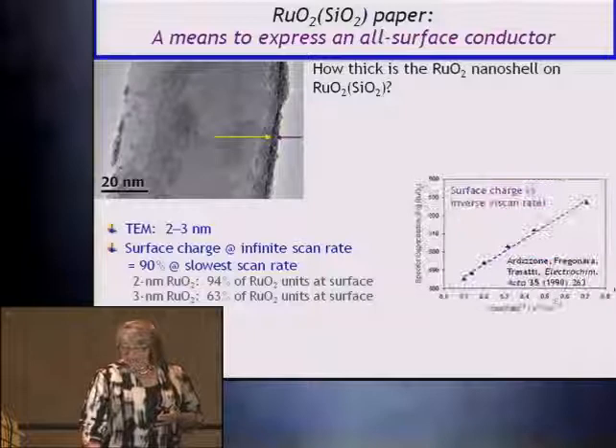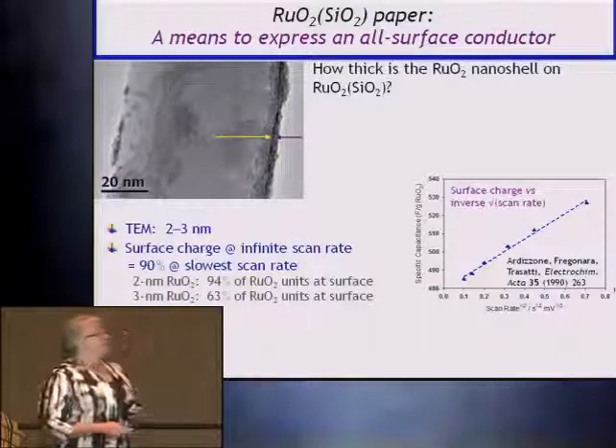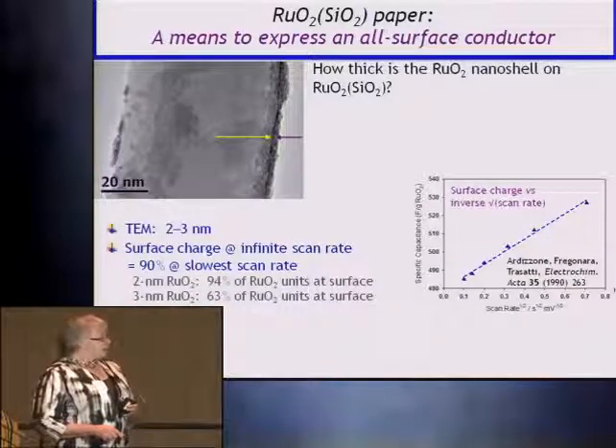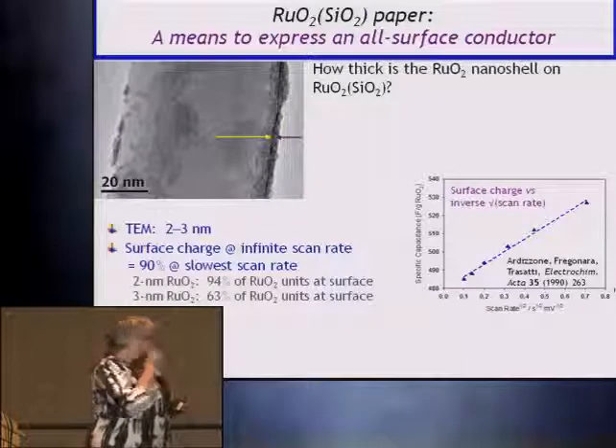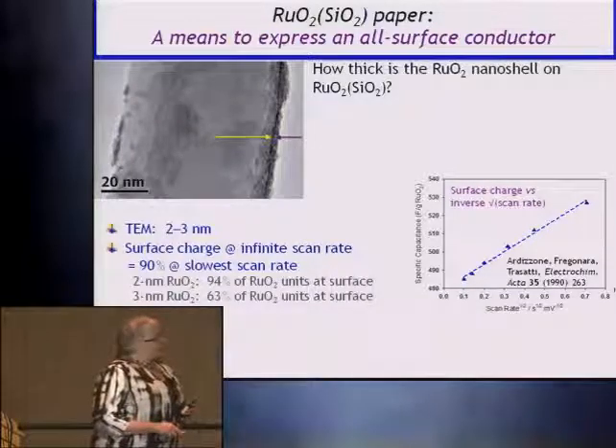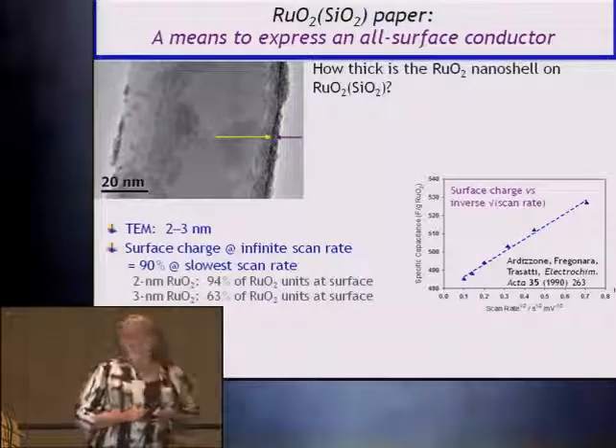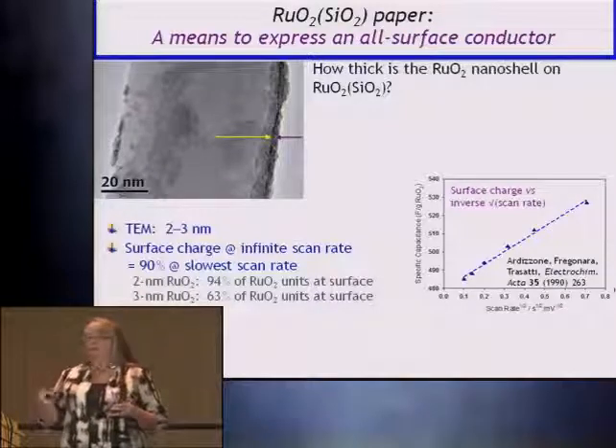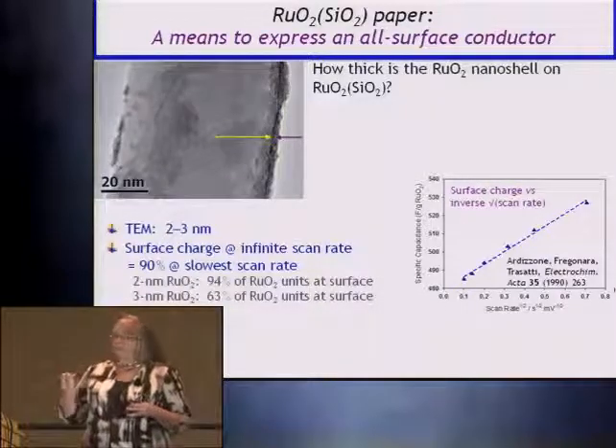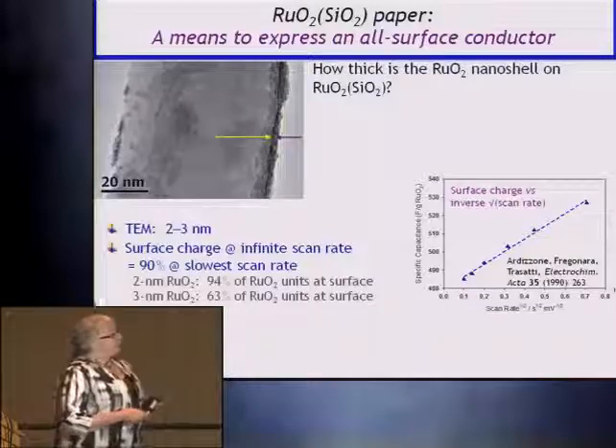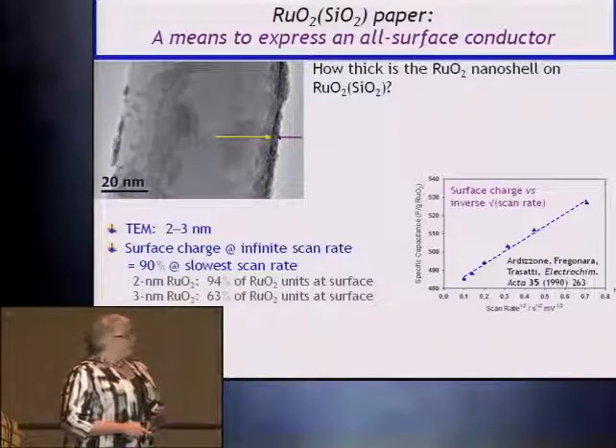So we applied the formalism that Trasatti taught us in 1990, where you plot 1 over the square root of scan rate and extrapolate that to infinite scan rate, because then you're only looking at the charge that is at the outermost surface. And when we do that, we see 90%. This extrapolated number is 90% of what we see at the 2 millivolts per second, which means this film is